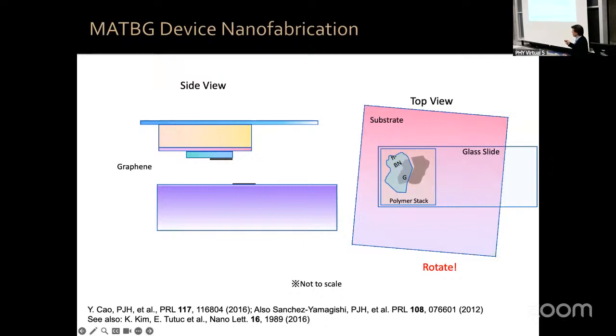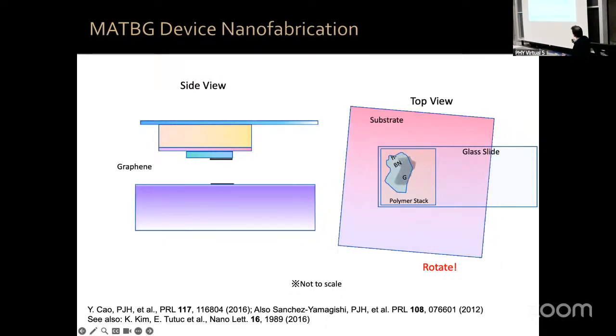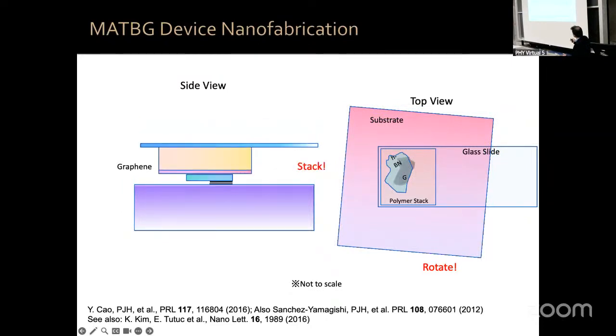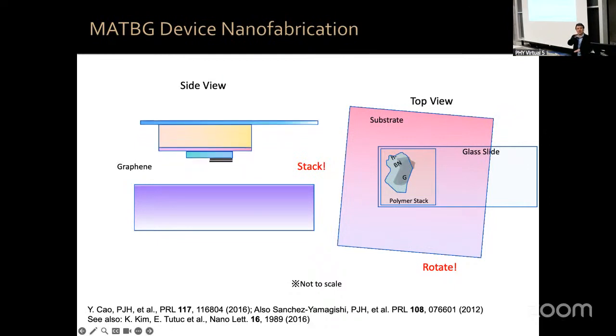So what we can do now is we can rotate our substrate by any angle that we want, for example, 1.1 degrees. And then we can translate this on top, and then we stack it. And we pick up the second half, the other half of the graphene. Amazingly, this produces this very fine, very precise Moire pattern at 1.1 degrees, where now the electrons are going to experience the strength of that Moire potential. And then you can continue doing fabrication in the standard way that we do with graphene devices.